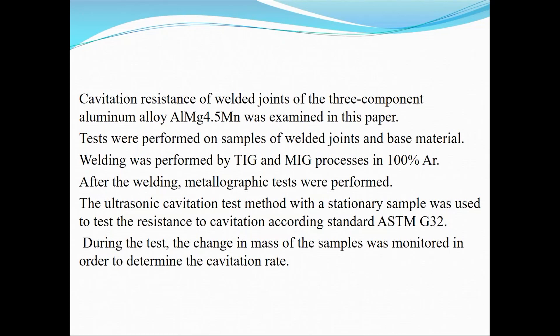There were two processes involved in welding of this alloy: TIG and MIG, both of them in 100% argon. There were also some metallographic tests that were performed, so that we could see how the fracture and damaged surface would look. The cavitation test itself was performed by ultrasonic waves using the standard procedure defined by ASTM G-32.